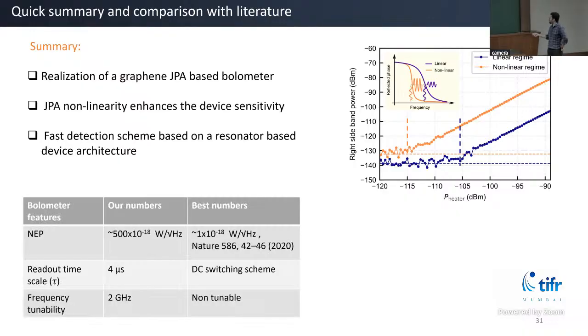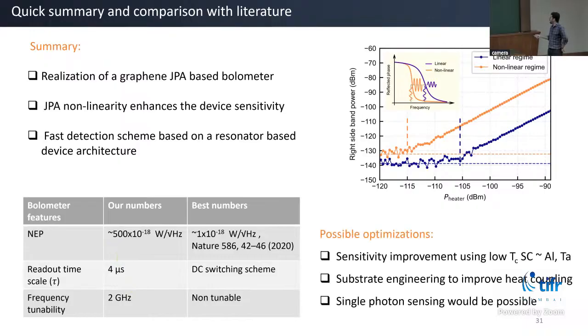If we compare with the best number in the literature, our NEP is currently not so good compared with this Nature paper, but our readout time is really fast, whereas they are in a DC switching scheme, like a quasi-DC experiment. Also, their devices are non-tunable; they use a fixed frequency resonator. So in these two aspects, we are doing well here. And there are some possible optimizations that we can do to enhance the NEP further.